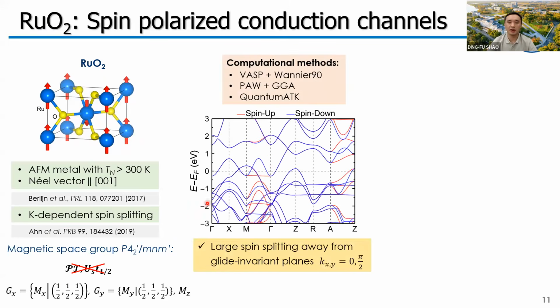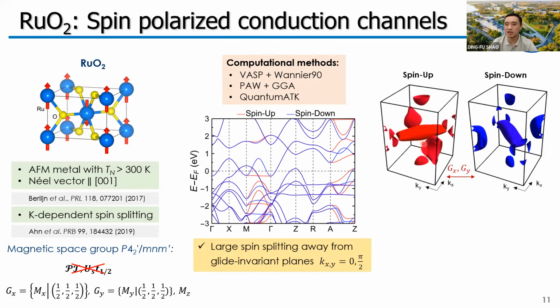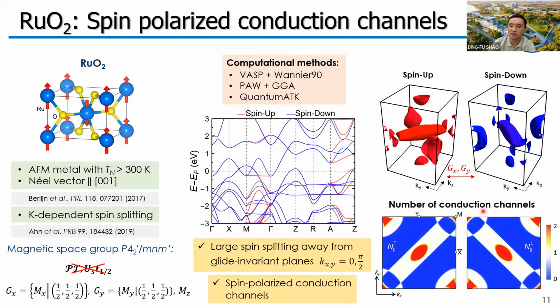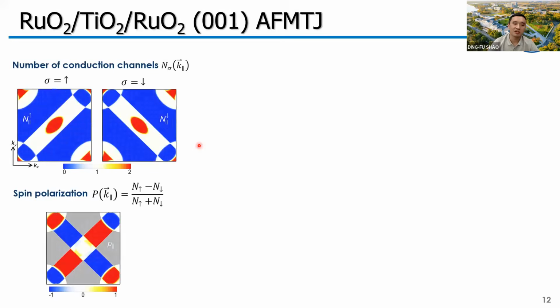And these symmetries allow a sizable spin splitting in the band structure along this direction, which will generate the non-spin degenerate Fermi surfaces. If we consider transport along the [001] direction, we can project these Fermi surfaces into the 2D Brillouin zone and get the number of conduction channels contributed from these Fermi surfaces. We can further calculate the spin polarization of these conduction channels. Obviously, the total spin polarization of all the conduction channels must be zero because the spins are anti-symmetric with the glide or mirror symmetries. But locally, most of the conduction channels are fully spin polarized.